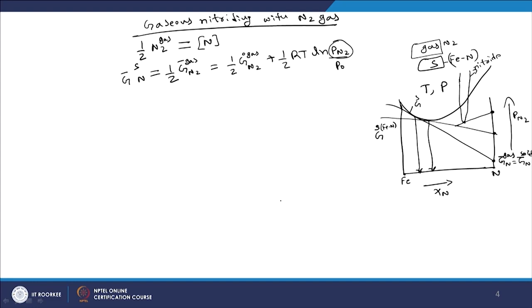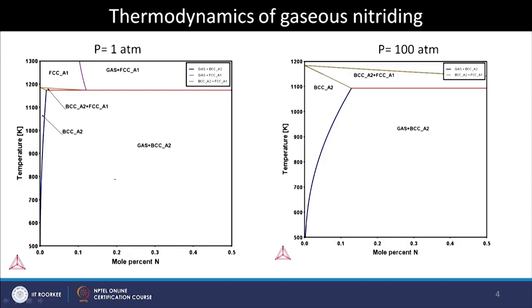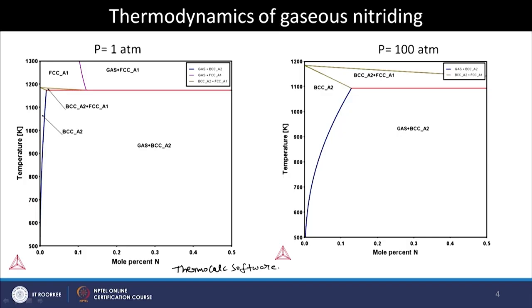This is how we can have different iron-nitrogen phases being synthesizable by changing the nitrogen pressure. Now, if you use one atmospheric pressure of nitrogen in actual situations, what is shown is the phase diagram of iron and nitrogen — temperature as a function of nitrogen content — showing all the equilibrium phases and their compositions at a given temperature and pressure combination. This phase diagram was calculated at a pressure of one atmosphere using the Thermo-Calc software with the TCFE9 database. This is what happens when we impose one atmosphere of nitrogen on solid iron.